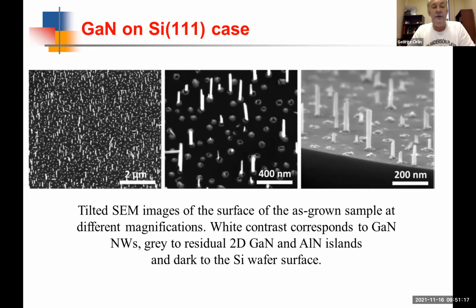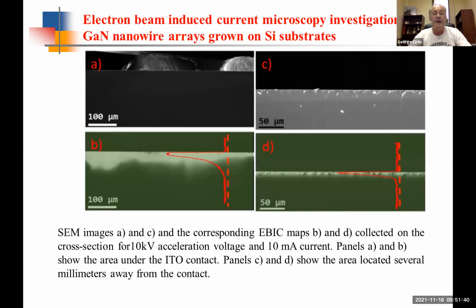And in fact, we did not see any significant signal from a piezoelectrical point of view. But what we found was that these nanowires were, in fact, N-type doped, even though we did not use silicon for the growth of these gallium nitride nanowires. And using the EBIC technique, which is electron beam induced current microscopy, we also found that not only do the nanowires exhibit N-type conductivity, but also the substrate was extremely highly doped, at least at the border between the nanowires and the substrate itself.